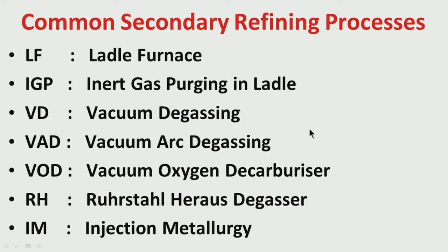Then we can have the vacuum oxygen decarburizer, VOD. What does it do? There is vacuum as well as you are passing oxygen. So, this helps in decarburization. That means oxygen will react with carbon, will generate carbon monoxide, which is a gas. And if you have a vacuum, this carbon monoxide removal becomes easier. So, it is an efficient process for decarburizing.